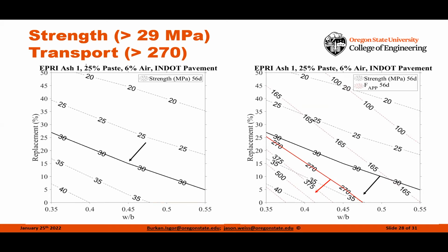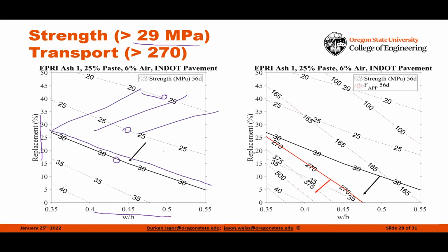So here again, this is an off-spec ash, right? And what we've done is we've plotted the water to binder ratio on the x-axis. We've plotted the SCM replacement level on the y-axis, and these contour plots are the compressive strength of the system. 20 megapascals, 25 megapascals, 30 megapascals, right, all the way up. Now, if we say that all of our mixtures have to have a strength that's greater than 29 megapascals, we can essentially draw our line here and say everything up above this line would fail to meet that criteria, right?